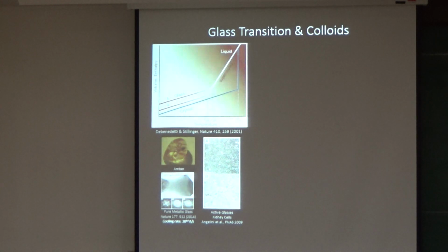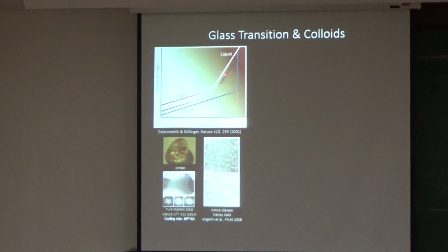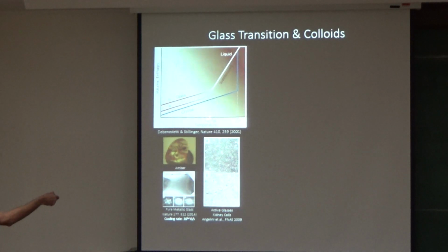So, okay, the trouble with superheating is that what intervenes is that you always have a free surface. So you're never able to superheat the crystal until you maintain a boundary condition which prevents the system from melting. So you need to really cool fast, you need to basically suppress the formation of a nucleus, because in this regime, the crystal is the stable thermodynamic state. So in this you don't have a free surface.